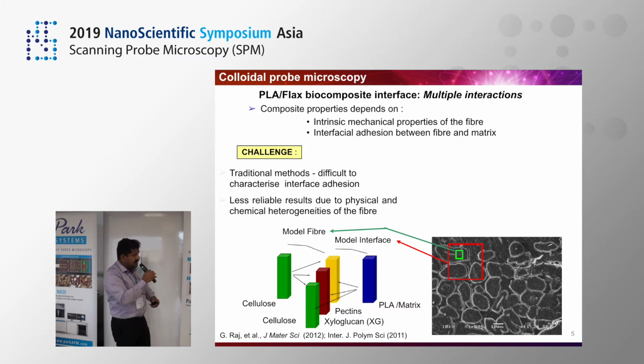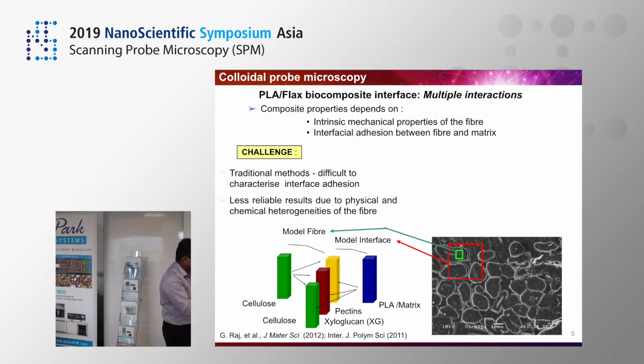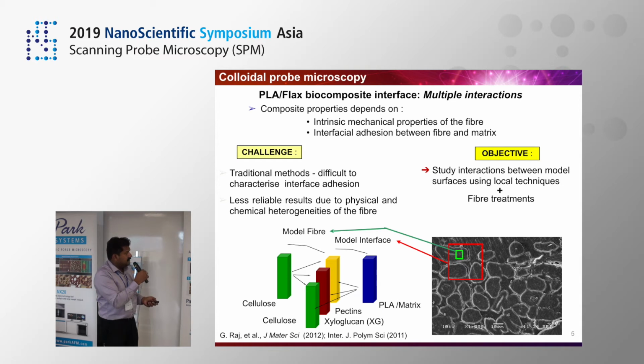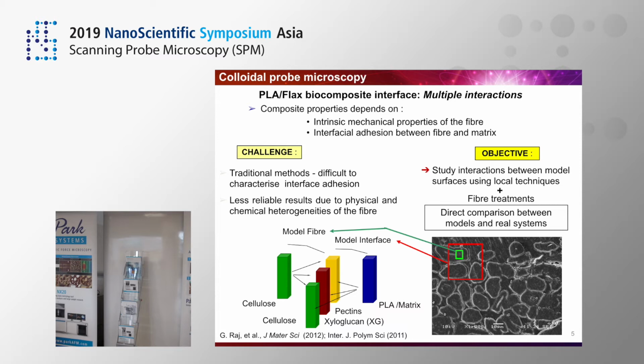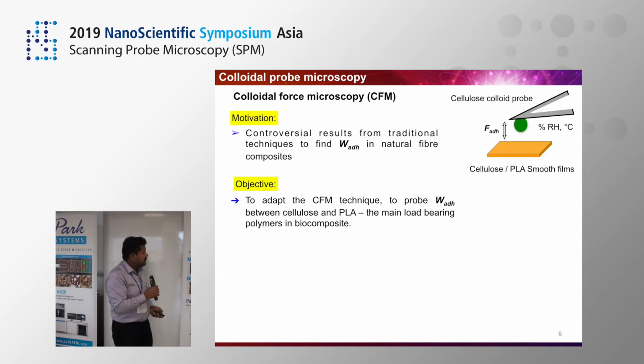Traditional methods are difficult because they are ensemble techniques. So we need more local techniques to probe specifically interactions between these pairs. Our objective is to study interactions between model surfaces using local techniques based on AFM, which allows us to give a direct comparison between model and real systems. So here is a colloidal probe technique. Basically it involves sticking a colloidal particle of interest, which can be a polymer microsphere, at the end of an AFM tip. And then we have a smooth film, essentially molecularly smooth films with the minimum roughness possible. And then we do the force distance measurements.